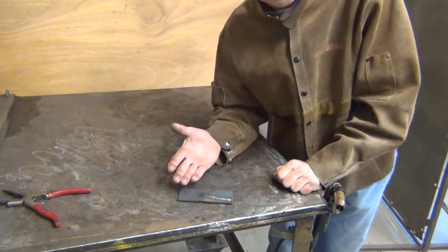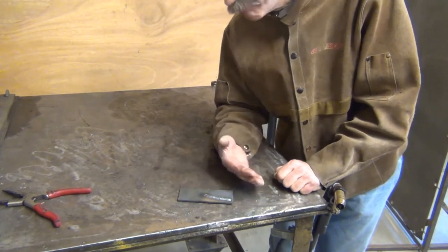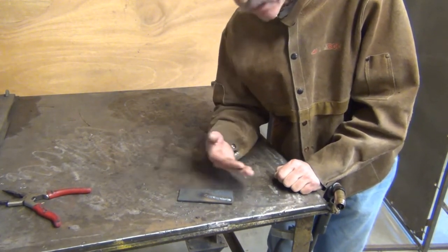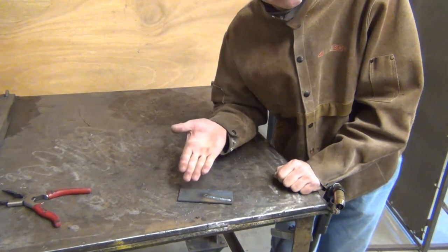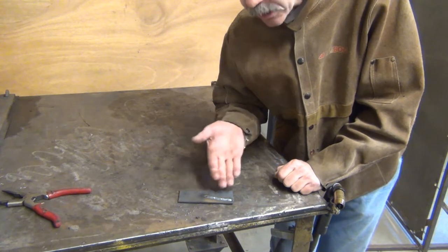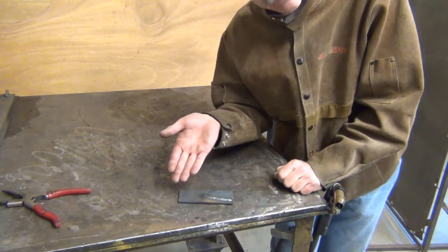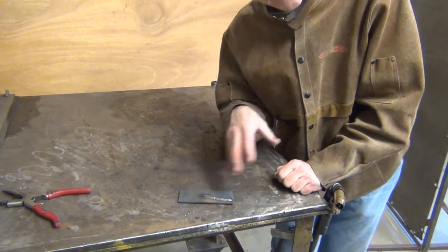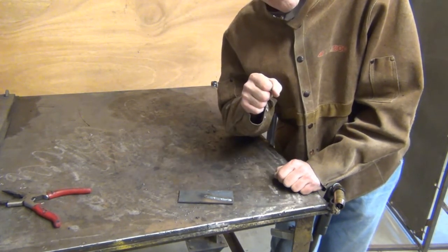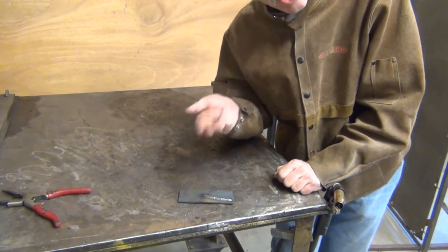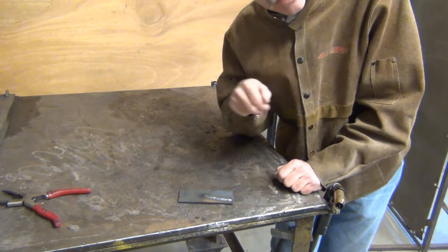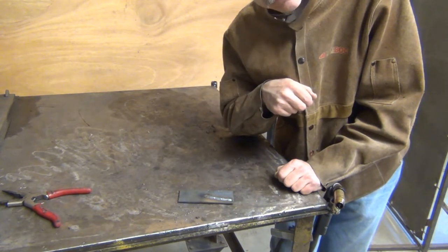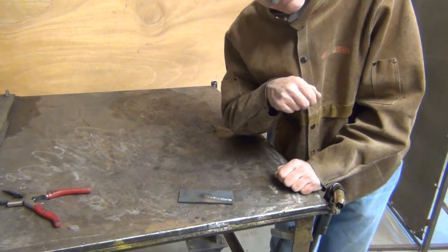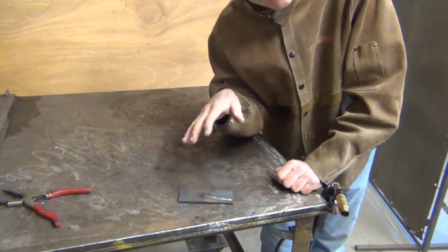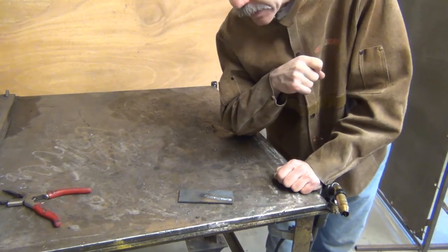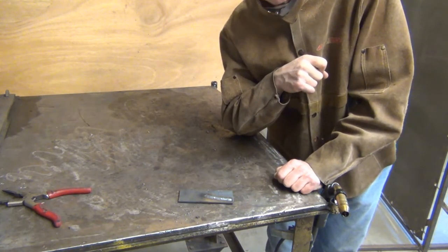Now, if the weld doesn't matter, it's just a temporary weld or something, yeah, you could stitch it. But if this was going to be subject to vibration, if you were welding this onto a piece of equipment and you didn't clean off the mill scale and there was any type of movement or vibration even, it may be in very short order that you're observing cracks in that weld. And that's because you didn't clean off the mill scale. Okay? I'm not going to bother for this demo. There's no need. But we do have disc grinders there that make quick work of it.